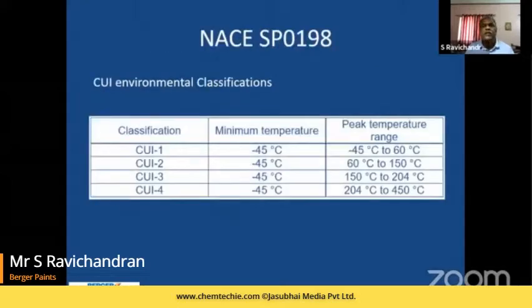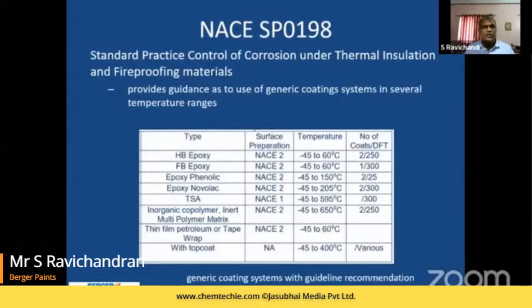So classifying that as per NACE SP0198, we have different temperatures, and the CUI classification of 1 to 4 gives you a temperature range for which we may have to address with different types of coatings. Now, SP0198, the practice of corrosion control under thermal insulation and fireproofing materials, gives you a broader understanding. There are high-build epoxies, epoxy phenolics or novolacs, thermal spray aluminiums, and inorganic copolymer matrix. These are products which are available in this area as of now. These generic coating systems with the guideline recommendations have to be followed when we look into options to stop this corrosion.